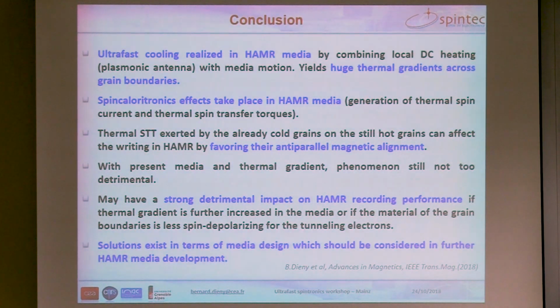To conclude, ultrafast cooling realized in HAMR media by combining local DC heating provided by a plasmonic antenna with the media motion allows to create huge thermal gradients across the grain boundaries up to 100 Kelvin per nanometer. And as a result of this, despite the polarization of the tunneling electron not being very high, 11%, the gradient is so high that we generate a quite significant thermal spin current across the grain boundary and also a thermal spin transfer torque. And this tends to induce antiparallel alignment between the already cooled grain and the grains which are still hot, close to the Curie temperature. And this phenomenon really has to be taken into account seriously in the design of the media. And several ways to improve the media have been proposed to reduce the impact of this phenomenon.